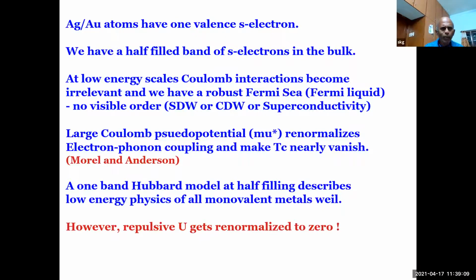So now let's think about pure gold. So if you look at gold and silver, it's very special because we have a half-filled band of s electrons. You can apply band theory, tight binding model very comfortably. And at low energy scales, you can show rigorously that Coulomb interaction becomes irrelevant. And you have a robust Fermi liquid, nearly no spin density wave, charge density wave, or superconductivity. And the large Coulomb repulsion even renormalizes electron-phonon coupling constant because there is insufficient screening and make Tc nearly vanish.